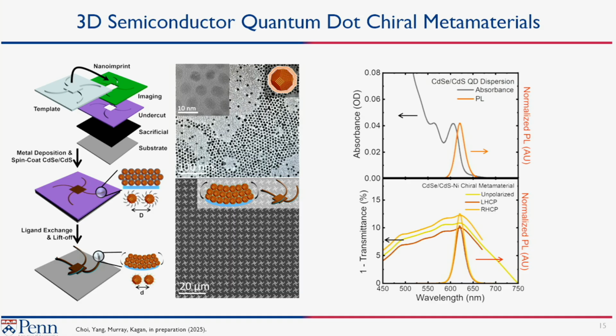This is work that we're trying to finish now. We built these materials from core shell quantum dots. Obviously we can tune the color of their emission, but in the examples here they also have about 85% quantum yield. You can see here the absorption and the luminescence of the constituent quantum dots that make up the structures that we built. That's these guys here. Then we can fabricate these into these structures, the same as I've showed you before.